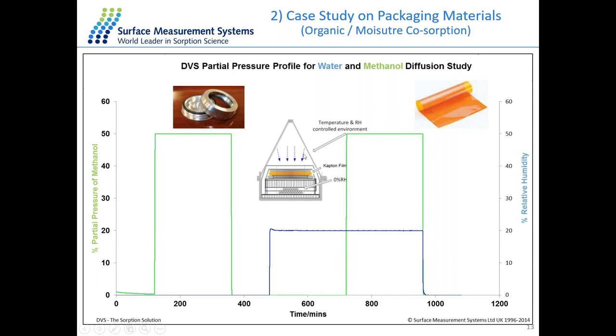So to set up the method, we created basically three different stages. The green line is for the partial pressure or concentration of methanol. The blue line is for the concentration of water. For the first stage, it's methanol only with 50% partial pressure of methanol. And the second stage is for water only with 20% relative humidity of water. And for the last stage here, we have two components generating at the same time. So we have 50% partial pressure of methanol with the presence of 20% water as the background.